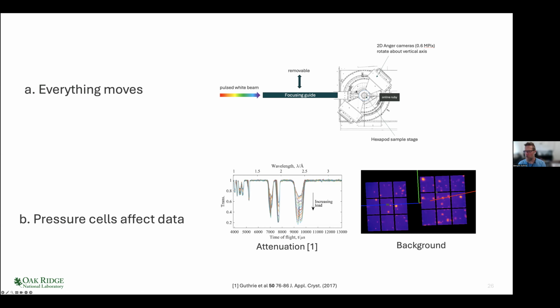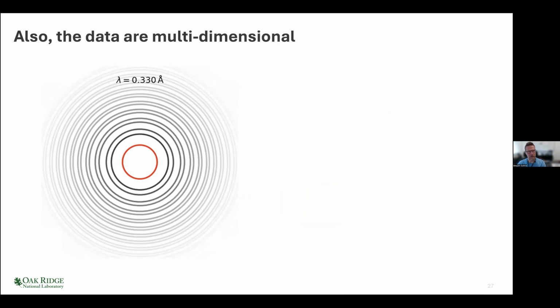And of course, pressure cells also give you a large background. And essentially what I'm showing on the right here is a data representation of what SNAP sees. So these squares are the two detectors. The green axis is vertical, the blue axis runs along the beam, and the blobs are all the diamond Bragg peaks. And those have to be removed from the data so we can access the interesting sample information content. And then the last reason it's hard is because the data themselves are multidimensional. So what I'm showing here is a simple monochromatic diffraction pattern representation measured on a flat image plate.